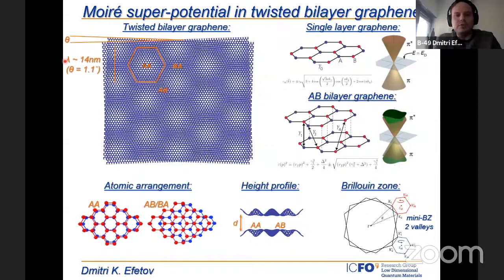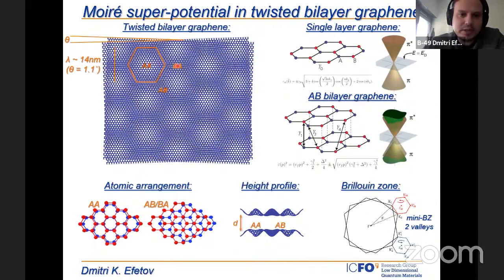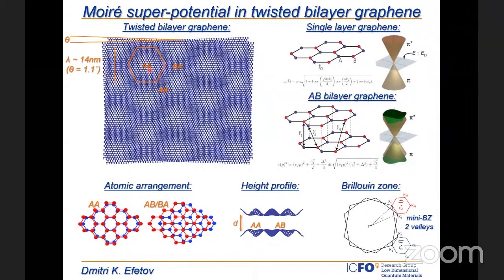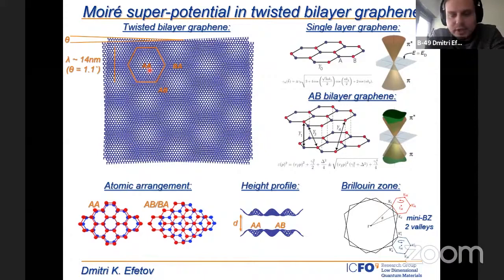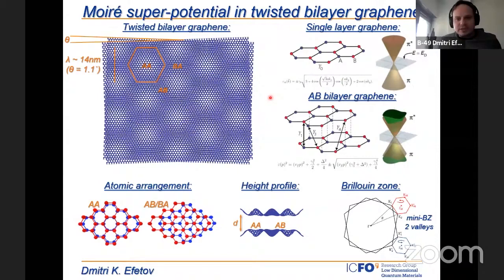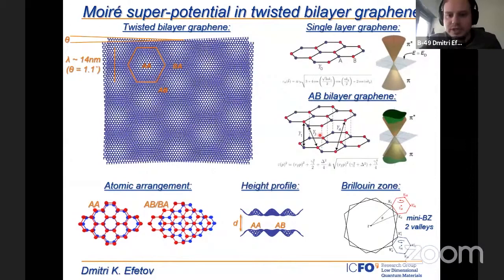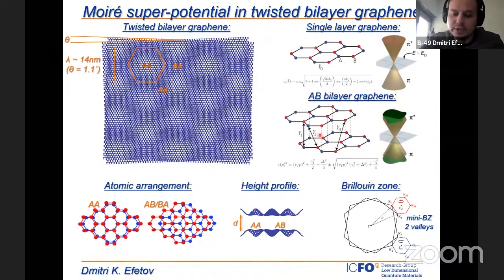The unit cells are extremely large, on the order of 10,000 atoms. We define AA regions where the top and bottom layer are directly on top of one another, and AB regions where the top and bottom lattices are slightly shifted towards one another. This periodicity gives really strong renormalizations to the band structure. In the Moiré system, tunneling terms are now an oscillatory function of the Moiré potential, and these changes in the hopping terms between the lattice regions bring really strong reconstructions to the band structure.